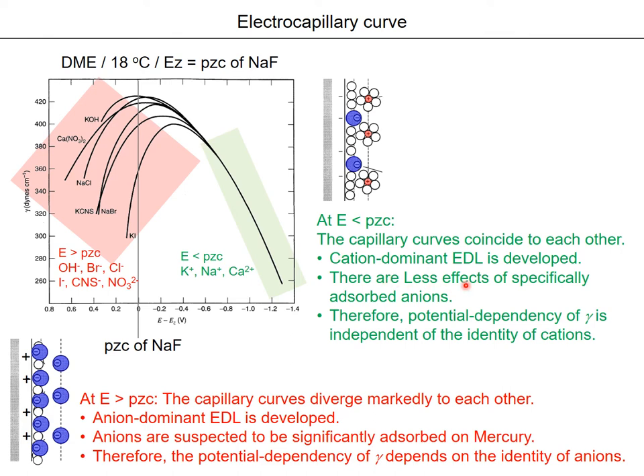There are fewer effects of specifically adsorbed anions. Here are the specifically adsorbed anions, and the number of adsorbed anions is not such a large amount. So there is less effect of anions in this case, because you have applied the negative potential to the electrode. There would be some repulsive forces. So statistically, a smaller number of anions could be specifically or strongly adsorbed on the surface of the electrode.